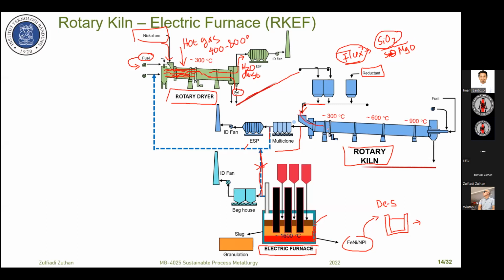And in this rotary kiln, we can see it later. The process in the rotary kiln is divided into 3 zones. The first zone is for the removal of surface water. The second zone is roughly to remove the crystal water, and the last zone is for pre-reduction and also to increase temperature. Maybe some of the crystal water will also be removed in this area.